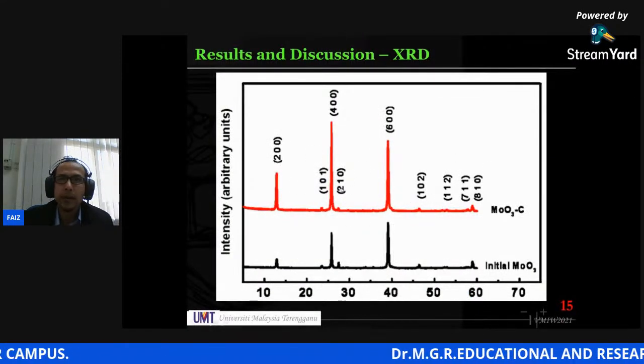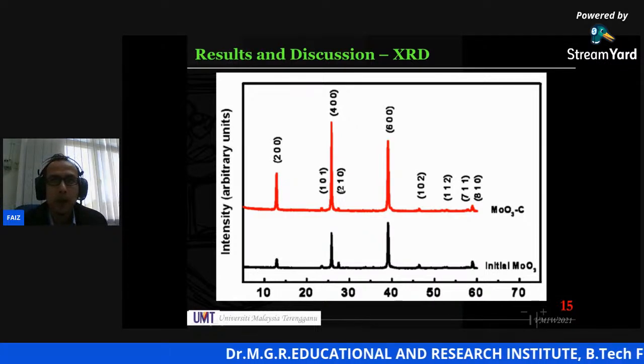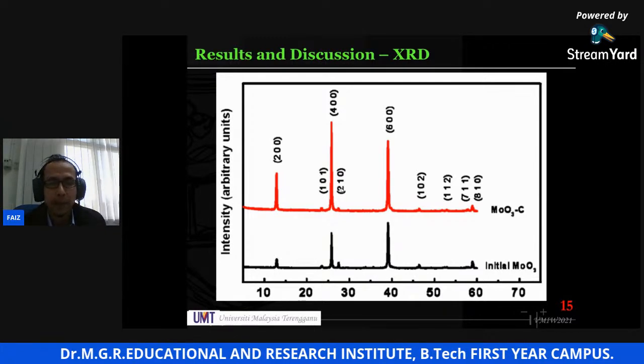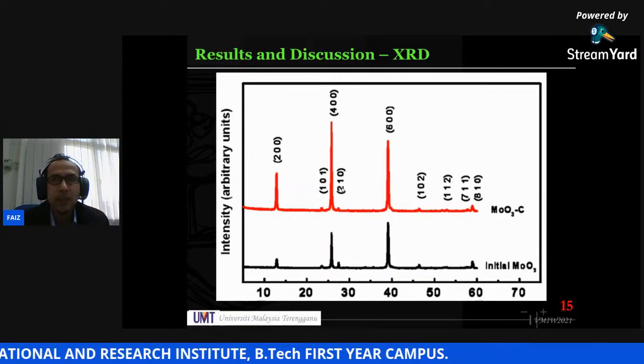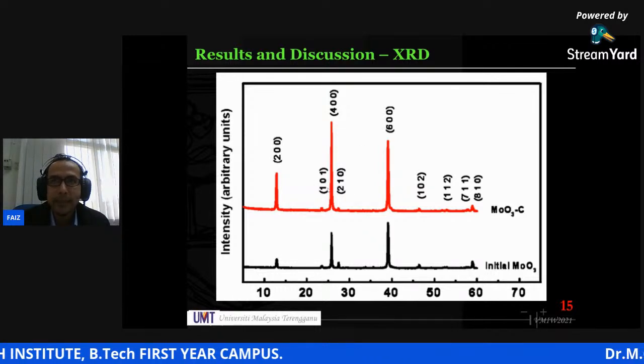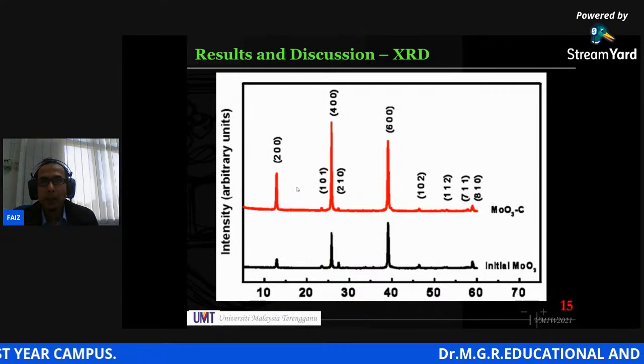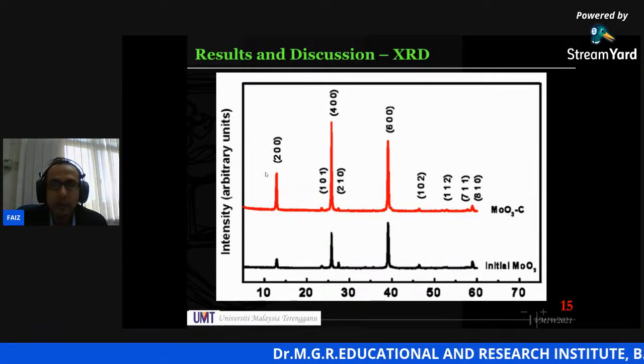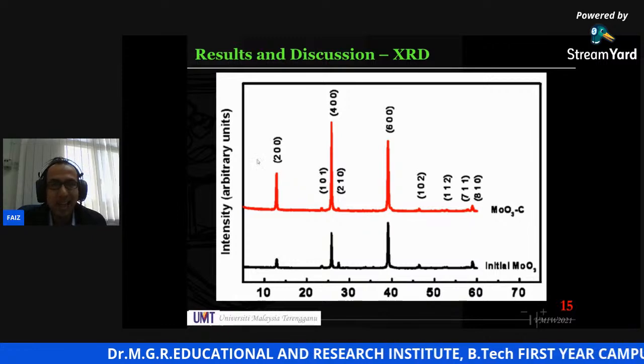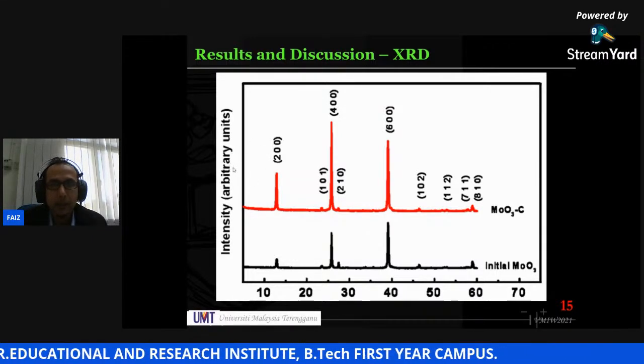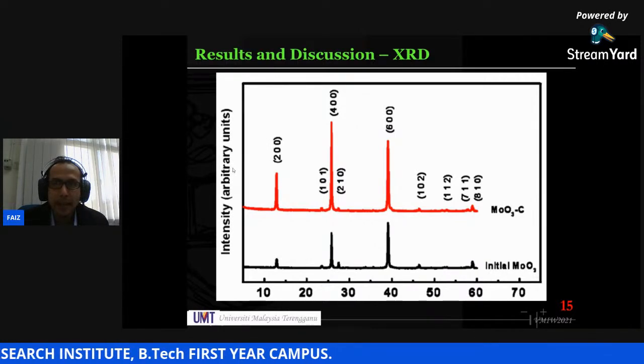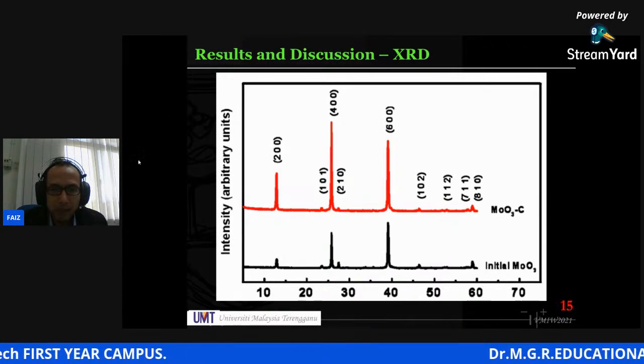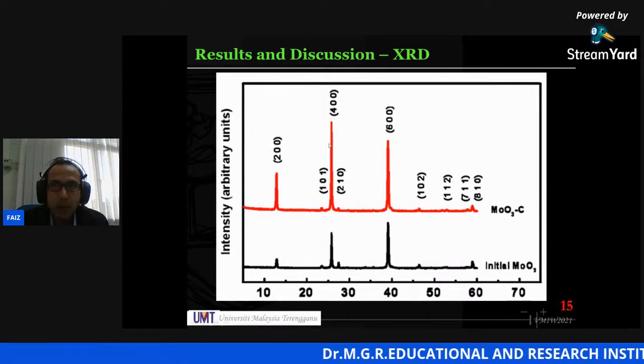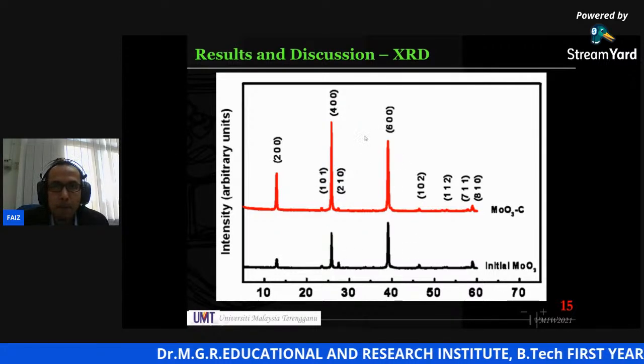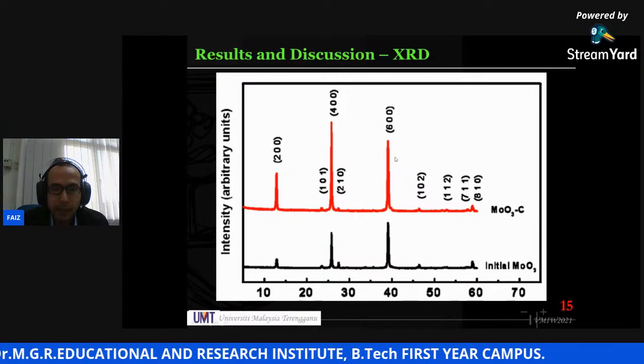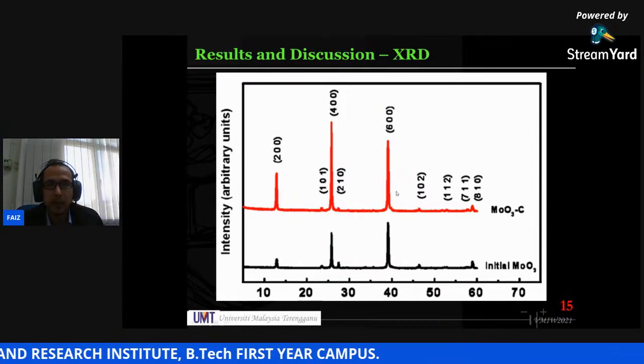All right, these are the results for carbon coated and non-carbon coated materials. As we can see from here, based on the carbon coated patterns, no carbon peak can be identified by XRD analysis. Basically, carbon is hard to trace in XRD analysis due to its highly amorphous nature, and also due to the greatly crystalline structure of the peaks for the bare molybdenum oxide nanobelts.